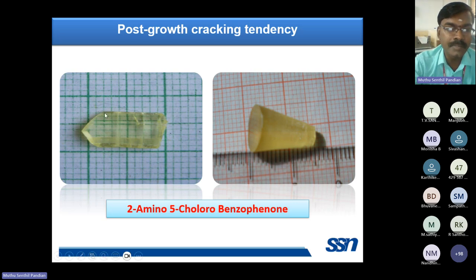So this is the conventional method grown 2-amino-5-chlorobenzophenone single crystal for nonlinear optical application. The SHG efficiency of this single crystal is 17 times greater than that of the standard potassium dihydrogen phosphate single crystal. When we grow the crystal by this conventional method, because of the temperature fluctuation, a small internal stress will be formed in the conventionally grown crystal that causes a large number of microcracks and milky opaques. But in the case of the SR method grown crystal, we have operated a uniform temperature at